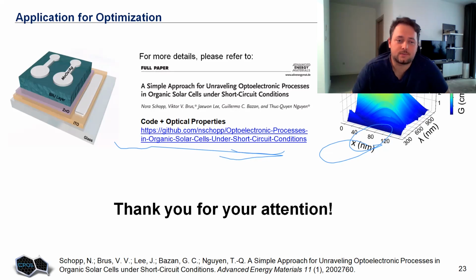The thing is that it sounds like quite a short recombination lifetime if you compare this to silicon, but keep in mind that silicon solar cells operate with an active layer of 300 microns in order to absorb all light and then convert it efficiently into electricity. However, organic solar cells operate with active layers of around 100 nanometers. So it's like 90, 110 nanometers, but as a rule of thumb, about 100 nanometers. So it's an extremely thin active layer. And even with such short recombination lifetimes, there is still enough time to extract charge carriers and reach quite high performance of about 18 or even recently published 19% efficiency, which is comparable to silicon.